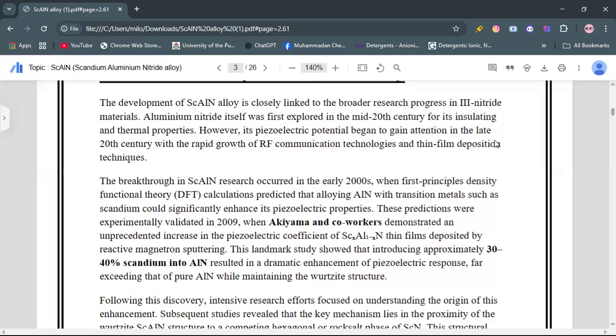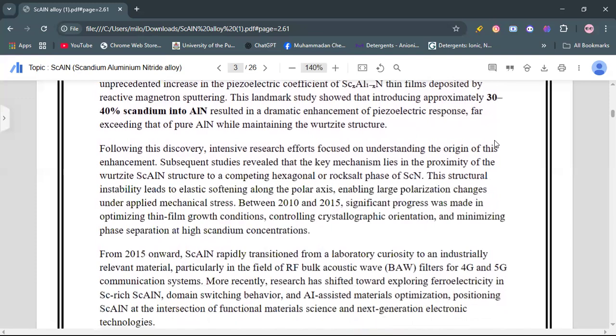This landmark study showed that introducing approximately 30 to 40% scandium into the aluminum nitride lattice results in a dramatic enhancement of piezoelectric response. Following this discovery, intensive research efforts focused on understanding the origin of this enhancement. Subsequent studies revealed that the key mechanism lies in the proximity of the wurtzite scandium aluminum nitride structure to a competing hexagonal or rock salt phase of scandium nitride. This structural instability leads to elastic softening along the polar axis, enabling large polarization changes under applied mechanical stress.